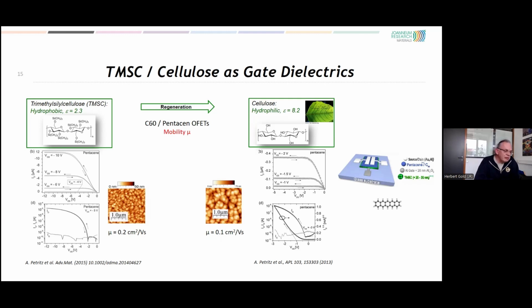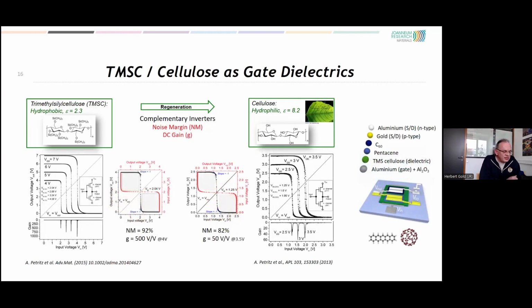This TMSC is quite a nasty material, and this was a demonstration, but at that time you could not make a reasonably thin and electrically dense layer out of cellulose directly. And another proof that this worked nicely was this organic complementary inverter with a very nice symmetry and a noise margin of 92%, and with cellulose still 82%, and a gain of 500, and with cellulose still 50. And so this was a result of quite early days.